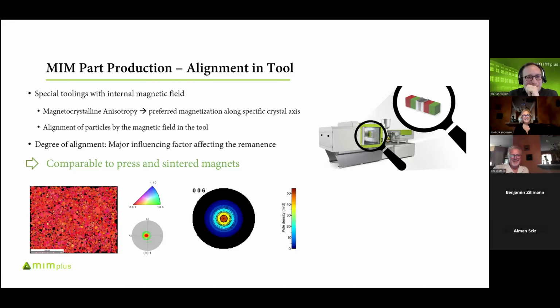But back to the alignment. We did some investigations via EBSD scans and also via X-ray diffraction in order to see how our alignment works. And from these experiments, you can extract a lot of parameters that describe your alignment in the magnet, and the result is that we are comparable to a press and sintered magnet with regards to our alignment.